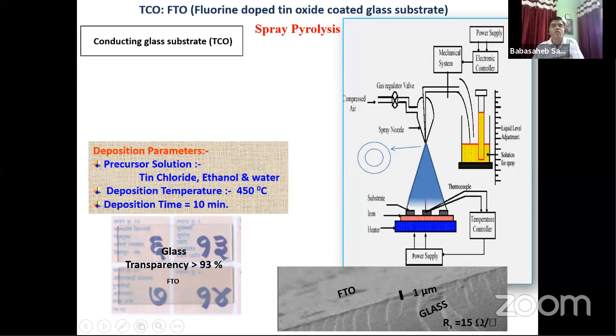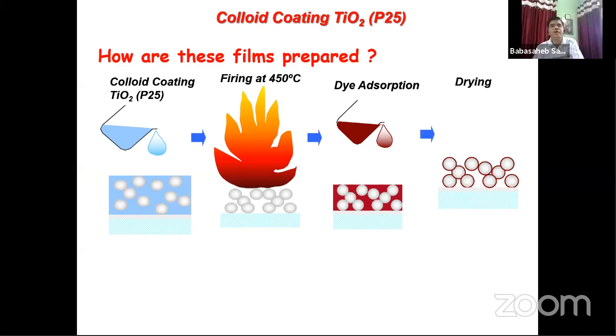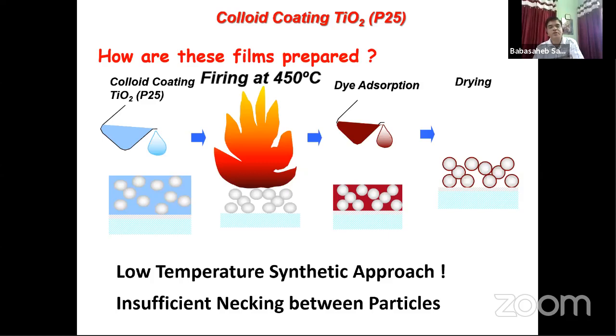So how to synthesize this zinc oxide, and why have we chosen it? Usually P25, that is Degussa TiO2, is used for this type of solar cell, which is fired at 450 degrees Celsius after coating on the FTO coated glass substrate, and then dye adsorption and drying. But whenever you want to use a low temperature process, there may be a problem of insufficient necking between the particles, and firing at 450 degrees Celsius is a very high temperature. If it is possible to reduce this temperature to maybe 100, then it is great, because in order to have a flexible substrate, you can use FTO coated PET as a plastic substrate, so that it is possible to bend this type of solar cell and make a flexible solar cell device in your hand, so that it can have a wide application.